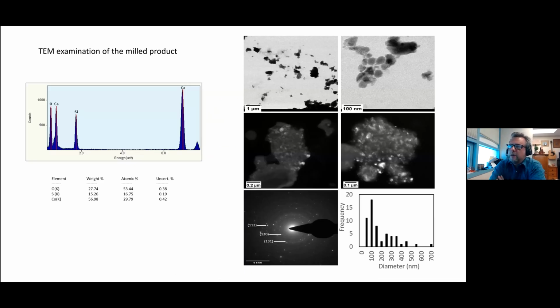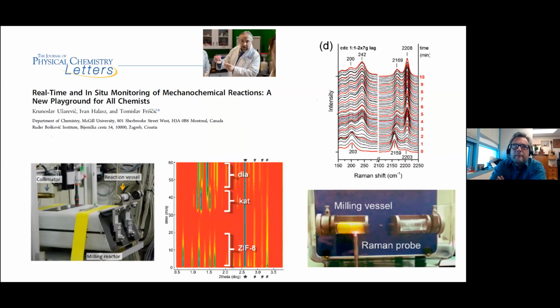So what we would like to do with this grinding approach to dynamic high pressure experiments in the future is to implement in situ observations. This is work done by Tomislav Friščić, which is really nice. They developed a synchrotron beamline where you can integrate a high energy mill and perform the grinding experiments while collecting X-ray data or X-ray and Raman data from the sample as it's being processed. So this would mean that we can see the progress of these transformations, either phase changes or chemical reactions, as they happen during the milling experiment.